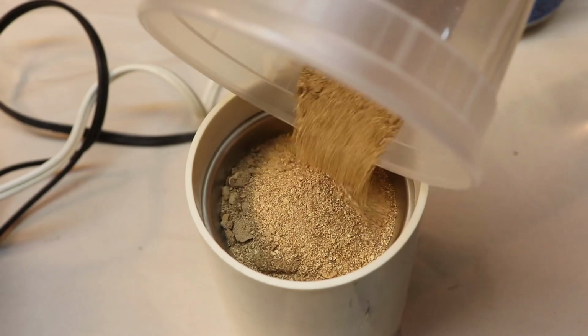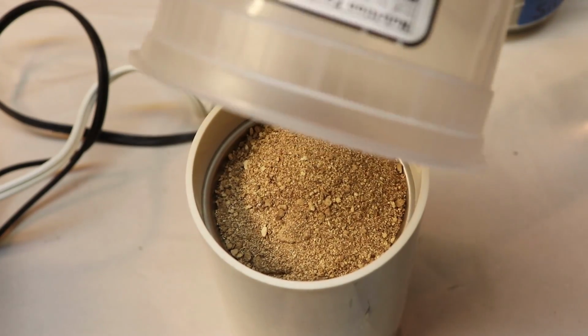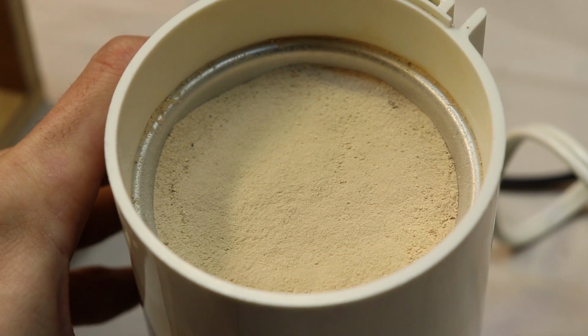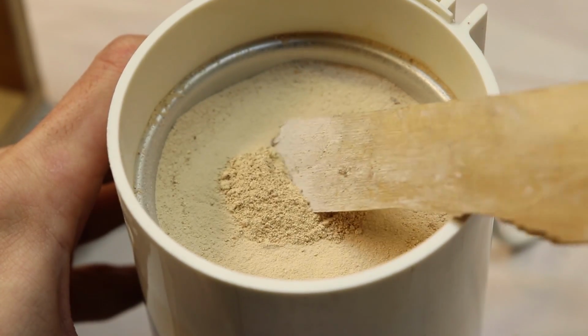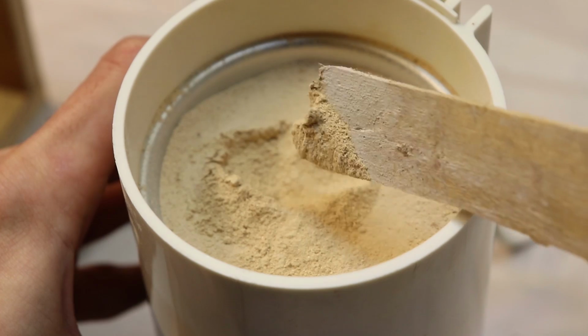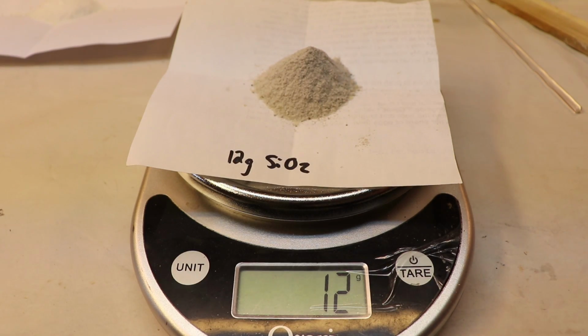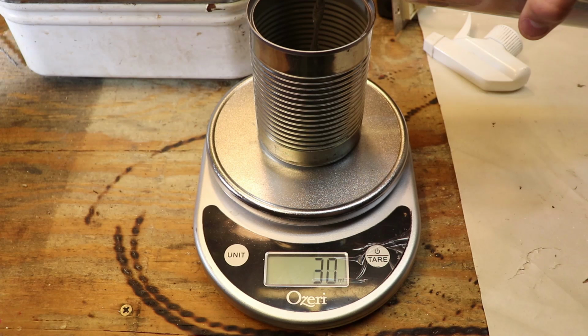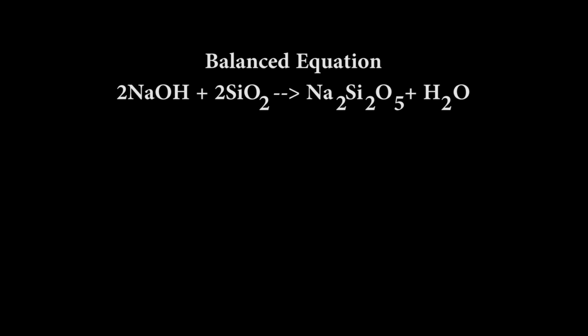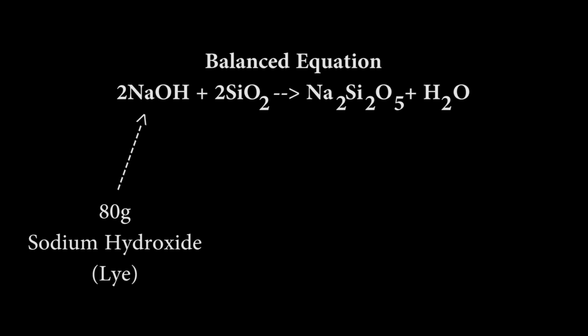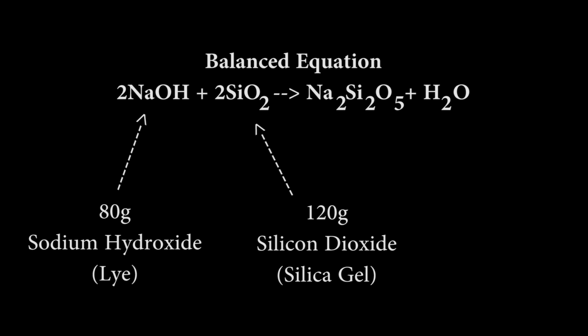Because there were still large chunks in the shredded eggshells, I decided to put them through the coffee grinder one more time, and that created a much nicer powder than before. Alright, so back to the sodium silicate. I measured out 12 grams of silica gel, 16 grams of lye, and 30 milliliters of water. Now, the proper stoichiometric amount is 80 grams of sodium hydroxide to 120 grams of silicon dioxide. But sodium silicate doesn't seem to care about stoichiometric ratios, meaning all ingredients are not completely consumed in the reaction, and you can play around with the amounts as desired for different results.